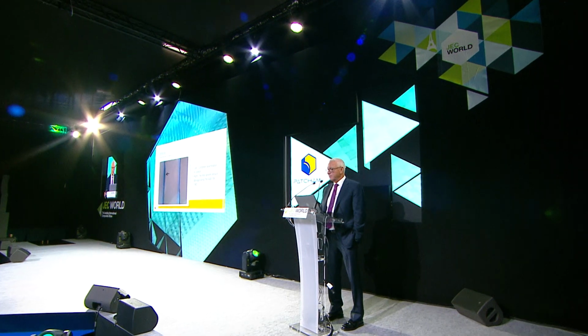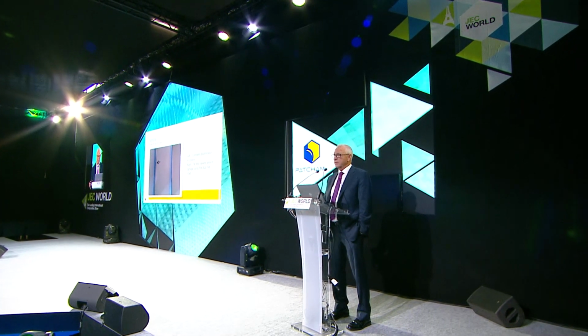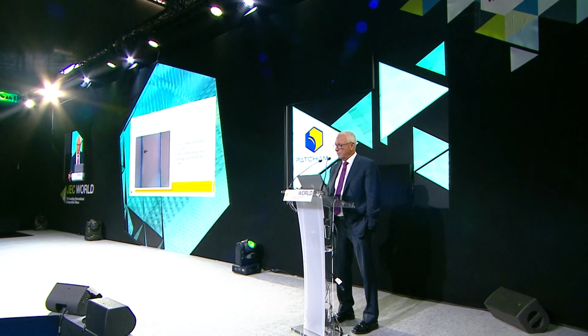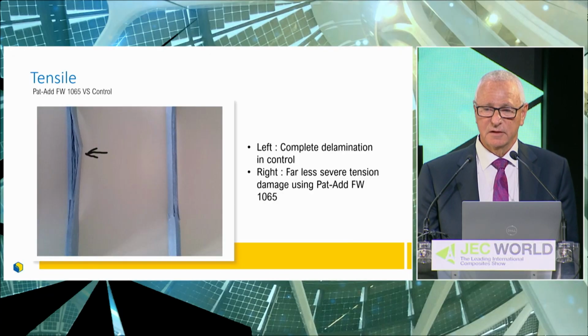Other interesting thing, when you look at these samples, I did kind of cherry pick these, but it was fairly common right across the board that without the additive, the tensile dog bones completely delaminated, whereas with the additive, obviously they broke because that's what the test does, but they tended to fail right where the grippers were, and they didn't, for lack of a better word, explode like the parts without the additive.